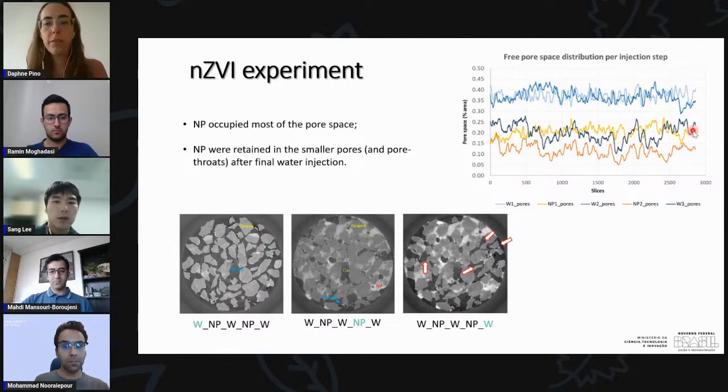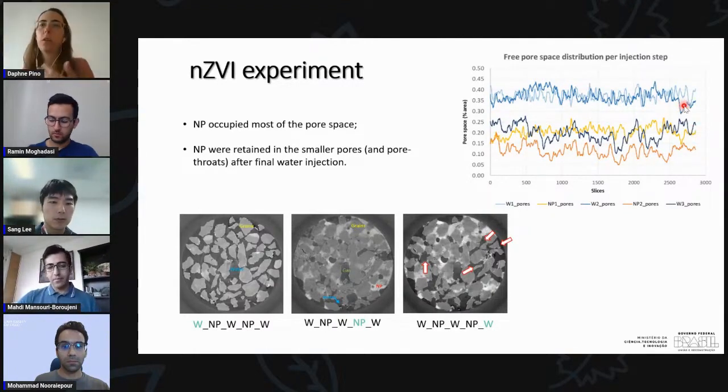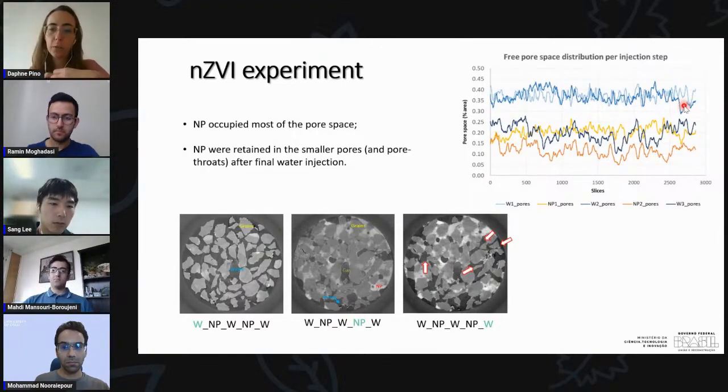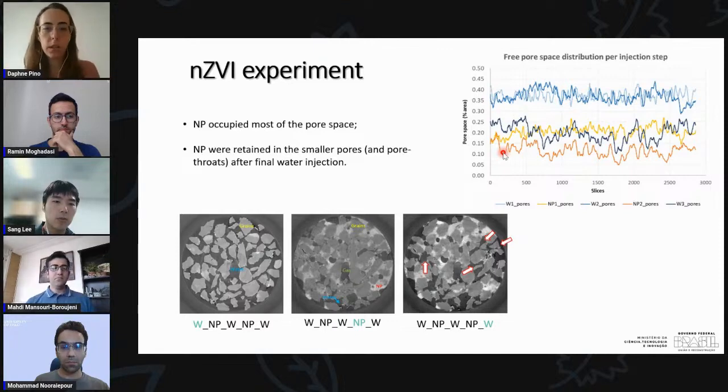And that's what we believe happens here, that nanoparticle history is very important. While it looked like the first time we were able to wash all nanoparticles away, that's not true, because some of the nanoparticles were actually retained in our media. And those nanoparticles that were still there were reacting with the new ones, and that was causing more clogging in our system.